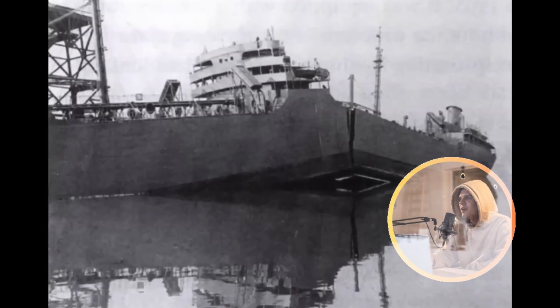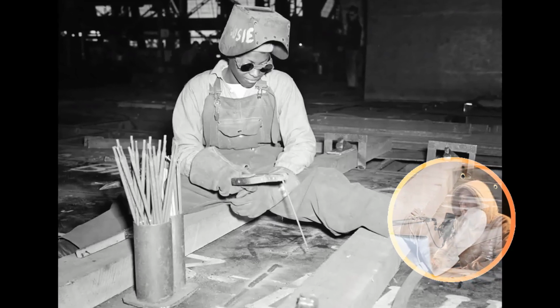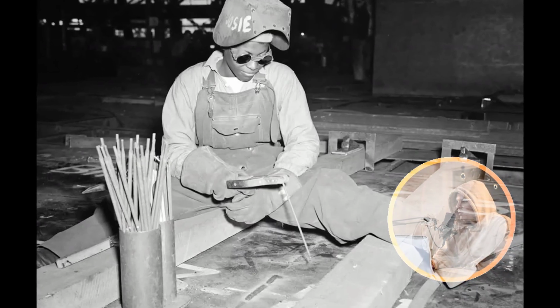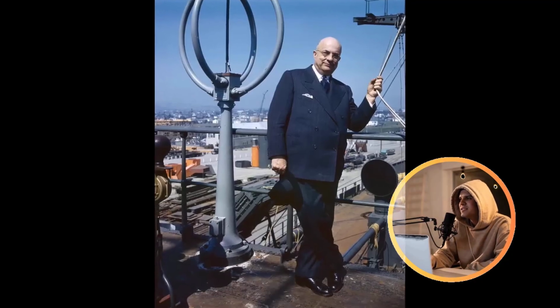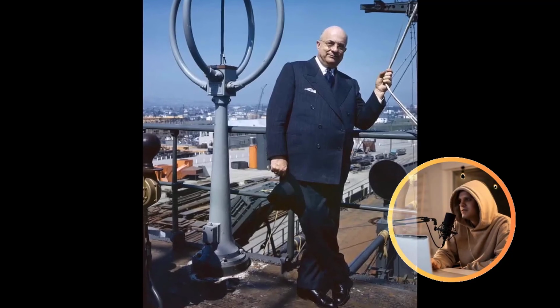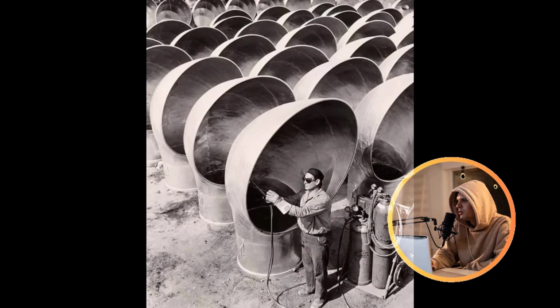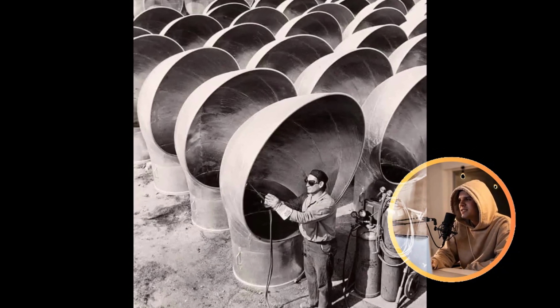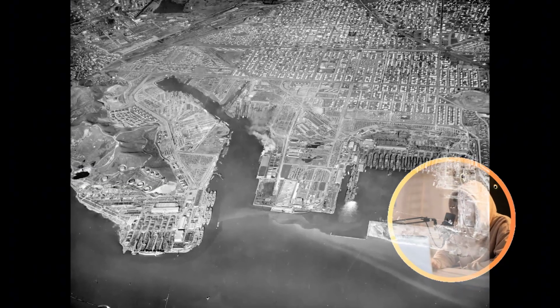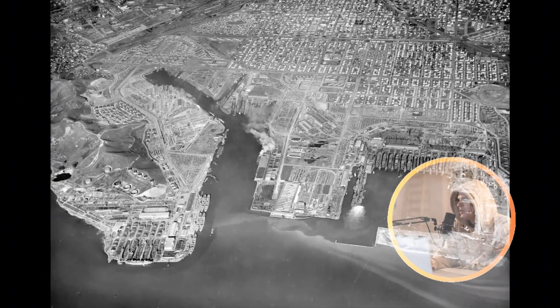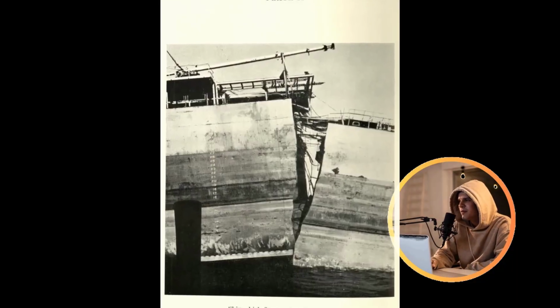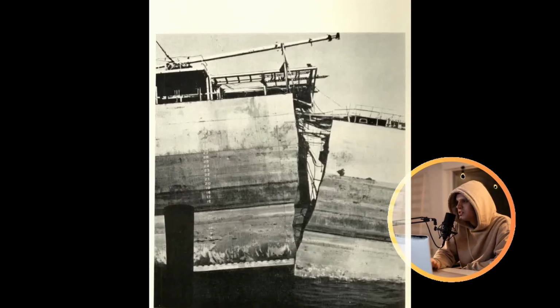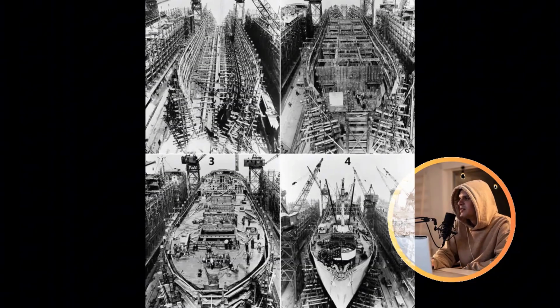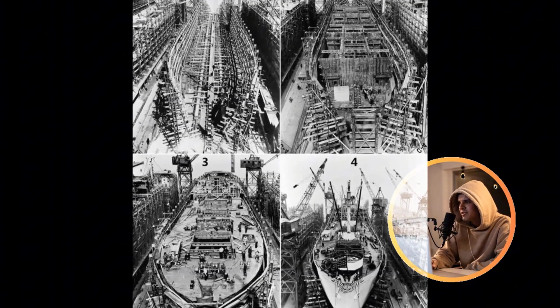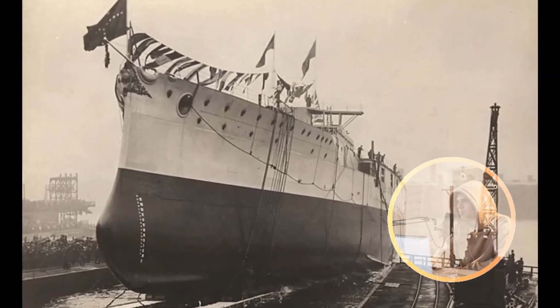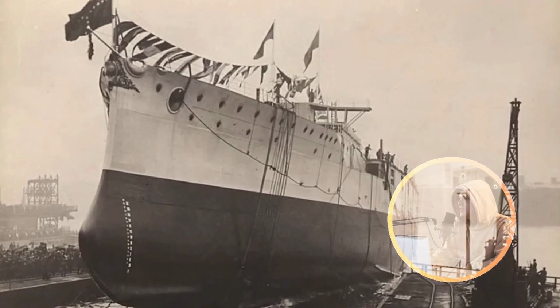When this brittle steel encounters concentrated residual stress at a sharp corner, such as the square edge of a cargo hatch, the laws of physics take over with brutal efficiency. A microscopic crack initiates. In ductile steel, that nascent crack would typically arrest itself, absorbed by the material's inherent ability to yield. In brittle steel under intense tension, however, the crack transforms into a sprinting fracture. The immense energy stored in those residual stresses provides the devastating fuel for the crack to propagate relentlessly. Sharp corners, acting as potent stress concentrators, multiply the local stress by factors of 3 or even more. The crack then accelerates, sometimes exceeding the speed of sound within the steel itself, racing through the hull before bulkheads or frames can possibly arrest its destructive path.